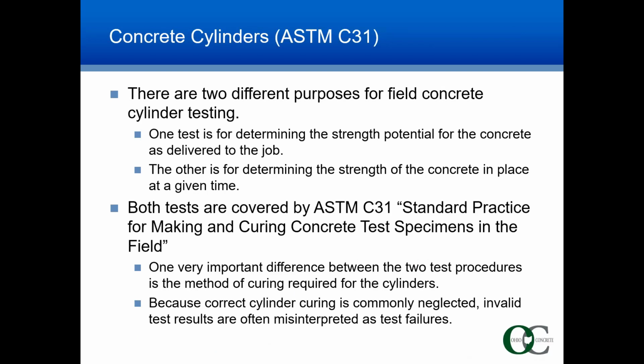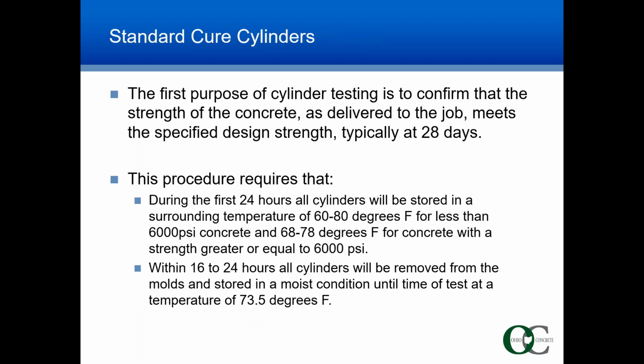Let's go ahead and take a look at concrete specimens. For ASTM C31, there are really two different purposes for casting field specimens. One test is to determine the strength potential for the concrete as it's been delivered to the job site, and the other is for determining the strength of the concrete in place at a given time. Both tests are covered under C31, and the one big difference between the two test procedures is the method of curing required for these specimens. Because correct cylinder curing is commonly neglected, invalid test results are often misinterpreted as test failures.